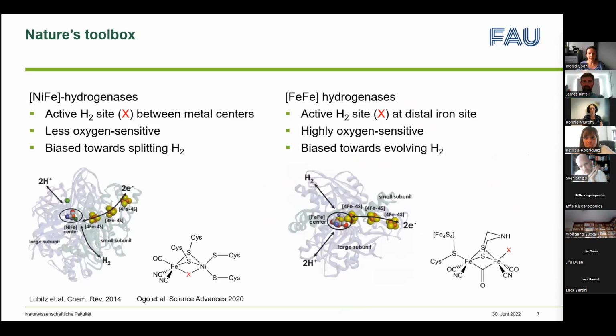So if we're looking at the bimetallic hydrogenases, we see that the hydrogen binding site is between the metal centers in nickel-iron hydrogenases. They are less oxygen sensitive and they're biased towards splitting hydrogen. Iron-iron hydrogenases have a different binding mode for the substrate. So hydrogen binds to the distal iron site, and they are highly oxygen sensitive and biased towards evolving hydrogen.